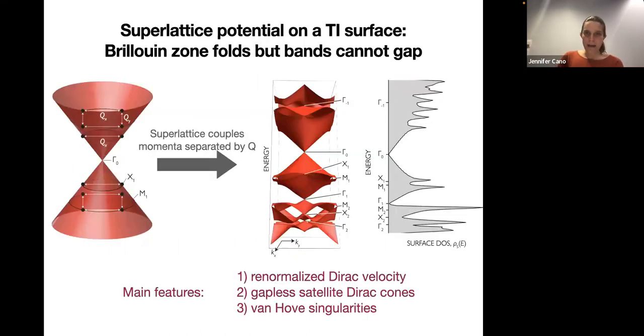Okay, so what happens when you put this superlattice potential? Just think about some potential which is modulated in space, not just in one direction, but in both directions. What happens when you put that on the surface of the TI? What that potential does is that it breaks translation symmetry. So your TI surface has this Dirac cone. Every point on this Dirac cone is labeled by a momentum K. We're used to K being a good quantum number, but if you break translation symmetry, different K points will couple to each other. And so the different K points that are separated by the wave vectors of the potential will be coupled.